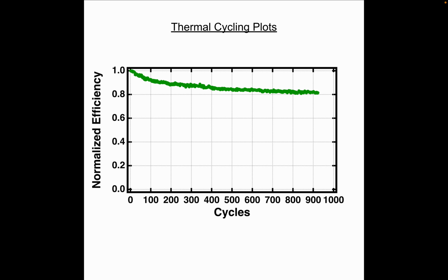The holy grail, the final answer, is that thing I've been hinting at, that thermal cycling temperature fluctuation. So one of the central points of this idea of harsh UV light, but specifically the temperature fluctuating rapidly, is measuring from around 0 to 60 degrees Celsius, and eventually we actually expanded that. When solar panels tilt out of the sun, satellites can change, and you see super big changes in temperature very fast. And so these are about 20-minute cycles. This is weeks of data, right? 900 plus cycles. And we were expecting about 75% retention. We were able to retain over 80% for this amount of pretty intense cycles.